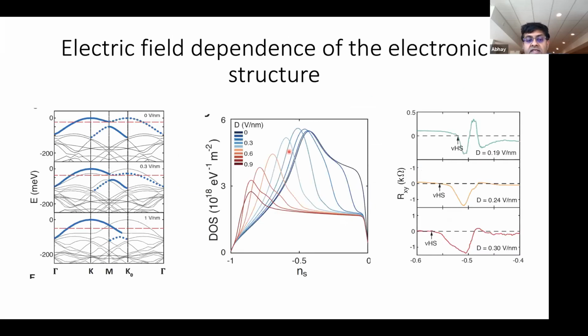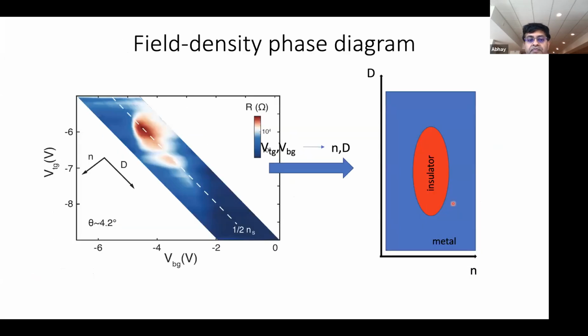And this is a busy slide. And all I want you to take away from this is perhaps this theory calculation, which says that as you apply different values of electric field, so these are the different colored curves, you can tune the density of states, you can tune the bandwidth by applying this electric field. And we were also able to show this experimentally that this is true. And what we found, this is again running a little fast, but let me just jump to the main point.